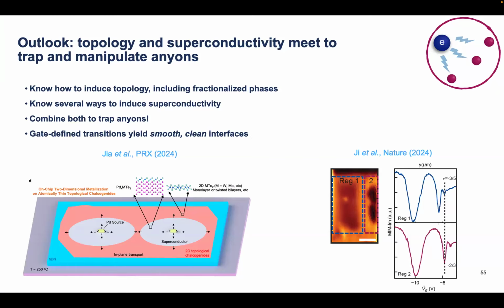I think you have good reason to not trust anything I say concerning these designs. But there's also good reason to hope that something will come out of those experiments, which is you want to proximitize a superconductor with a topological phase to create those anyons. So that's the main theory way we know how to trap those things. And there are two experiments that have shown that you can do things like that. With non-homogeneous gating, you can put two phases in close proximity. Those materials in their phase diagram sometimes have a superconducting phase, sometimes a fractional topological phase. So here you could hope that inhomogeneous gating allows you to put a superconductor close to a fractional phase, which I think is much harder.